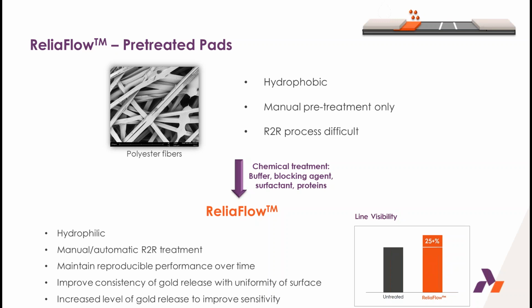And ReliaFlow is designed mainly to produce rapid rewetting of the pad during the use of the test, increase the level of gold release to improve the sensitivity on an average of 25% in the line visibility. ReliaFlow is also able to improve the consistency of gold release with uniformity of surface due to continuous automated application of the chemical solution. And finally, this pre-treated pad maintains reproducible performance over time.